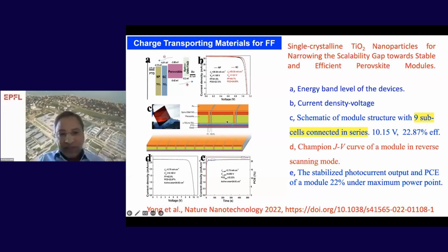They are serially interconnected, and that gives you 10.15 volts. So the voltage is quite high, and the power conversion efficiency is 22.87. This is one of the highest efficiencies for a mini module size of close to 25 square centimeters.